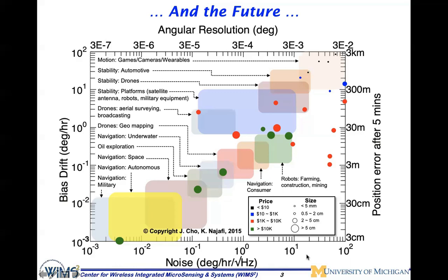If you make the device a little bit higher frequency, ring down time goes down, but quality factor actually exceeds 10 million. And again, this is a record, and amazing that one can achieve a quality factor of 10 million for a device at about 11 kilohertz or so. That's only about 10 millimeters in diameter. And this is indeed what then allows the use of these devices in very high performance gyroscopes.